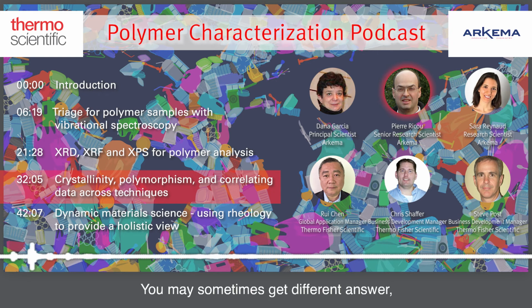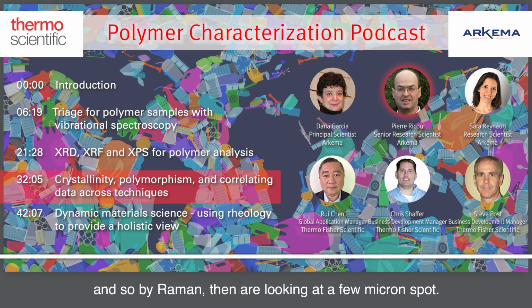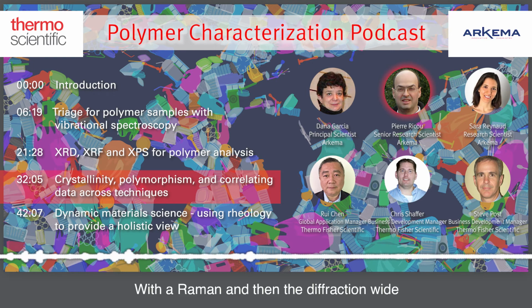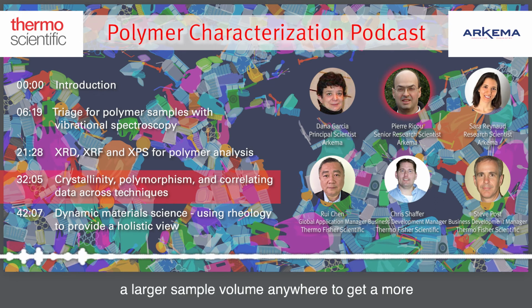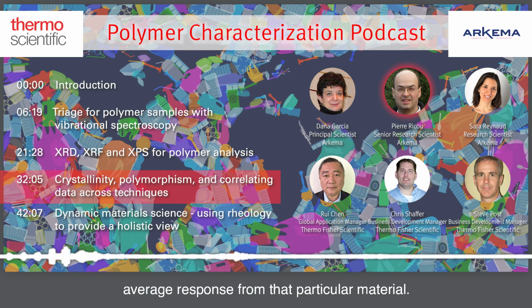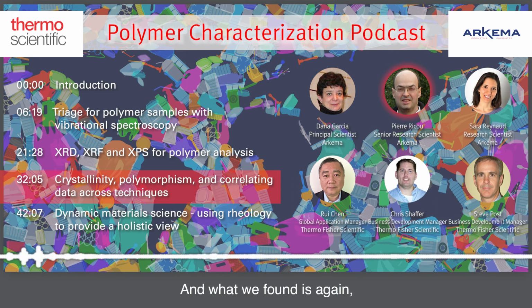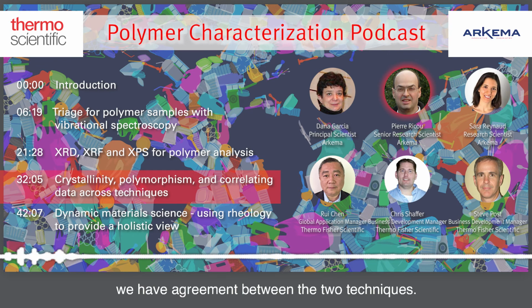You may sometimes get different answers, and I think it's based essentially on the fact that we are usually looking at different size scales. But if the material is homogeneous, then with Raman, Dana is looking at a few micron spot, and then a wide angle diffraction system typically runs a larger sample volume anyway, to get a more average response from that particular material. And what we found is, again, if the material is homogeneous, we have agreement between the two techniques.